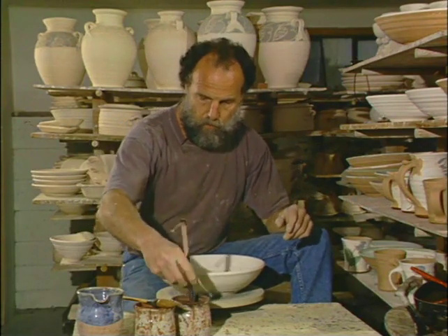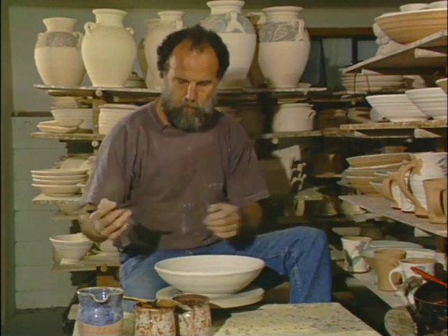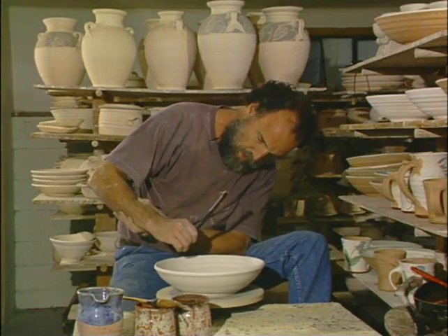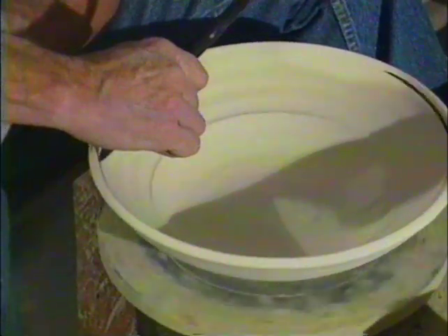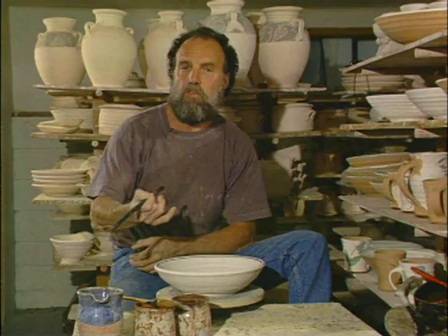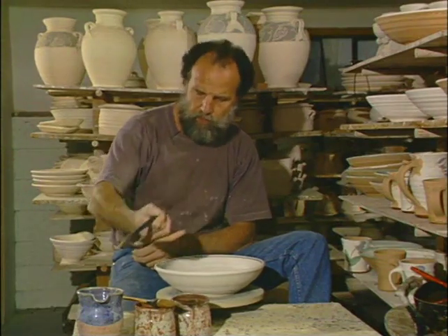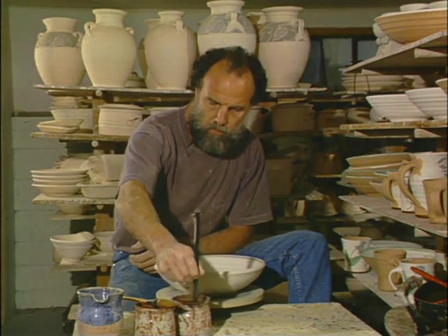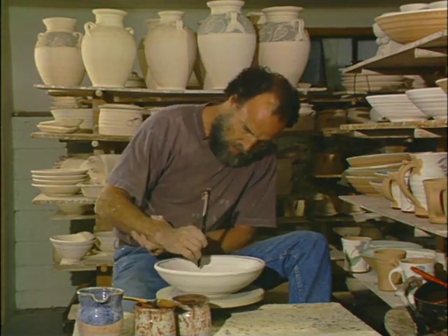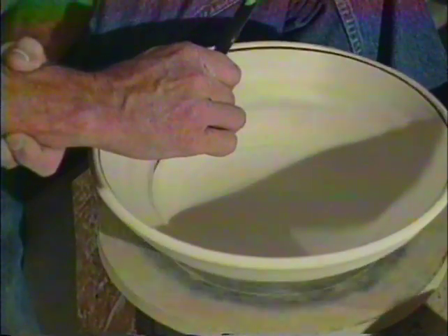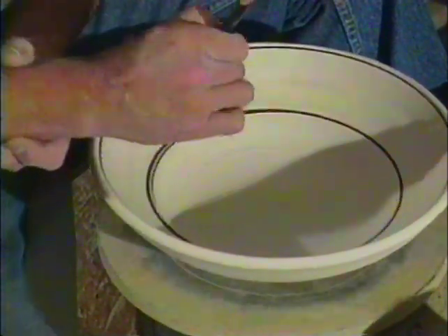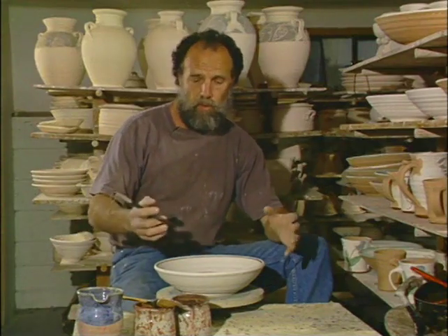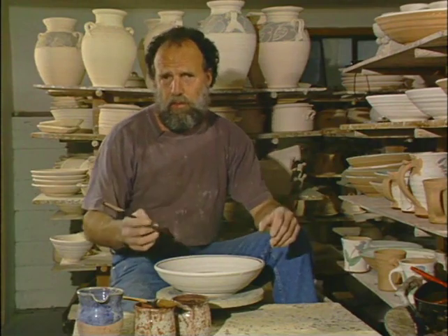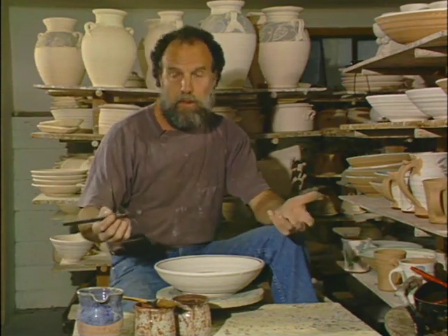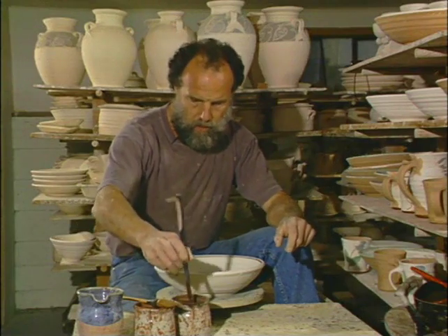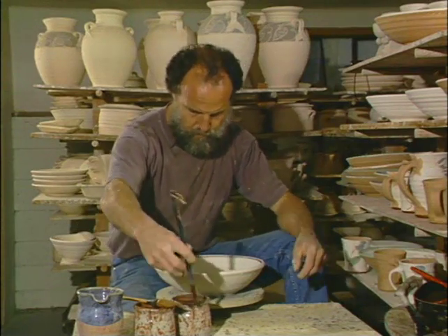Okay, so let's see what we can do with this pot now with a couple of blue lines on first. Again, supporting the brush with both hands to get a secure line. And you can really tell the consistency of the oxide is correct if it flows nicely onto the pot. The surface of a glazed pot is a particularly difficult one to apply decoration to because of the very absorbent surface, and you might find that before you go making irrevocable marks on a favourite piece, you might want to practice the decoration on some newspaper or something, dry paper. Okay, so we've got a couple of blue lines on there. Let's see.